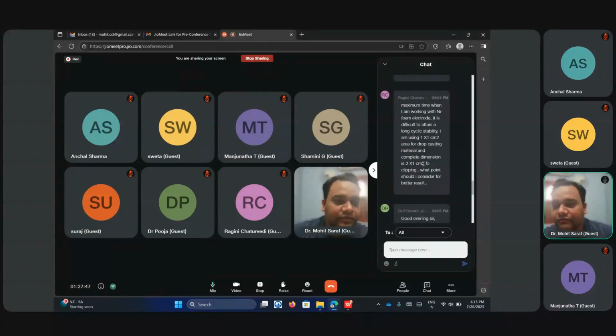Most of the time when I'm working with nickel foam electrode, it is difficult to attain long cycling stability. I'm using a 1 by 1 centimeter area for drop casting material, and the complete dimension is 2 by 1 centimeters for clipping. What point should I consider for better results? Honestly, I'm not a big fan of nickel foam, because I tried it once and I saw many papers, let's say MXene with nickel foam, and it shows you a redox signature. What is happening is it's a nickel redox rather than your MXene redox. Similarly, if you drop cast or coat your material on nickel foam and your coating is not optimized, maybe you are forcing nickel to give redox activity rather than your material, or maybe it is a combination of your material and nickel foam.